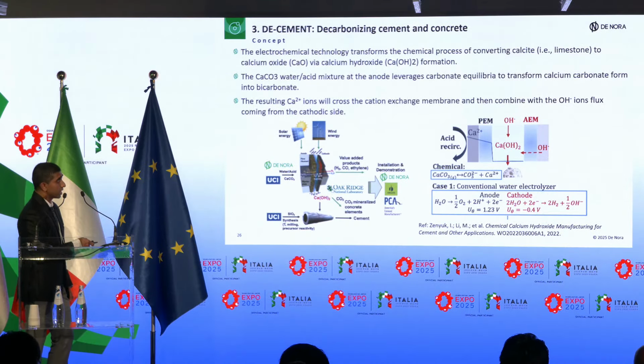Then we can heat up this calcium hydroxide and convert it to calcium oxide, which only needs to be heated up to like 400 degrees C. So when we do this precipitation reaction, we can run this reactor with oxygen evolution on the anode side and hydrogen evolution here, or alternatively, we can also consider doing CO2 conversion on the cathode side.